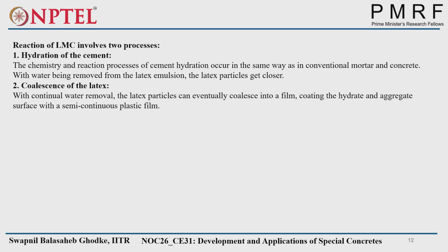Who will remove that water? That water will be removed or consumed by the cement particles for the hydration process. As that water is consumed by the cement particles for hydration, whatever dispersed polymer is available in that latex will get closer and form a semi-solid or semi-film around the hydrated or unhydrated cement particles. Next, coalescence of the latex.